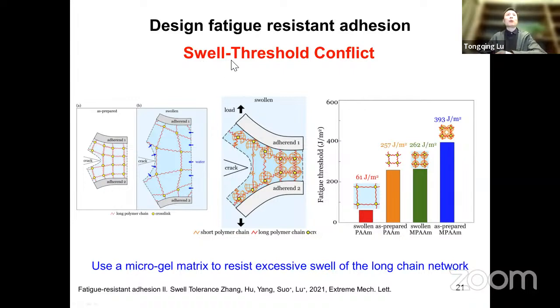So to resolve this swell threshold conflict, we follow the strategy of the double network design. We introduce some microgel matrix. Actually, this microgel is also another kind of hydrogel, and it is very stiff. So we combine two networks of hydrogel: one is the long chain PAAm hydrogel, and the other network is the microgel. The microgel will provide stiffness as well as very good swell resistance. So with this combination, we can simultaneously achieve very good fatigue resistant property and also swell resistant property.